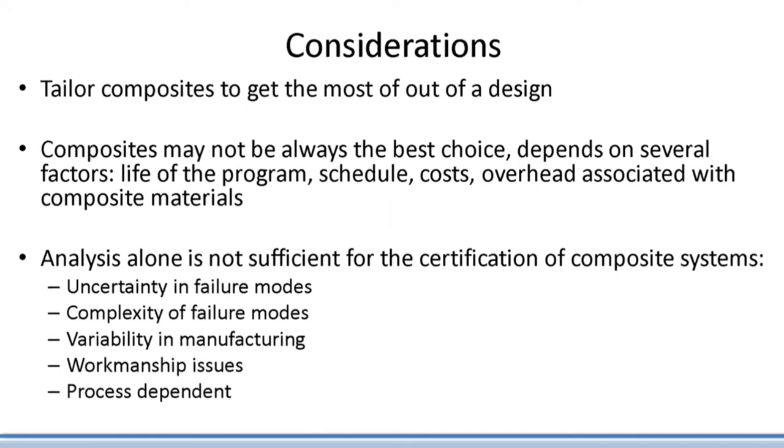And I already showed you a video that shows all the steps that it takes to make them. Even if there's a vacuum leak or a small imprint, or if the person did not use gloves and the grease was touching, or if they're using gloves but they're contaminated, or there's sealing paint that fell down onto the composite. All those things need to be looked at because it's going to affect the strength of the composite. Analysis alone is just not sufficient.